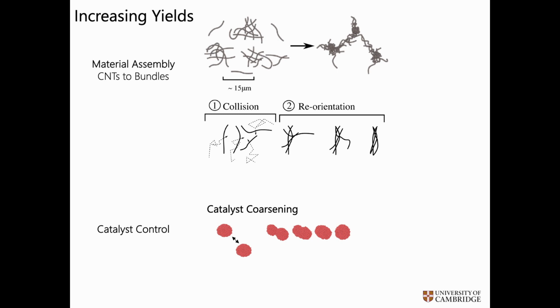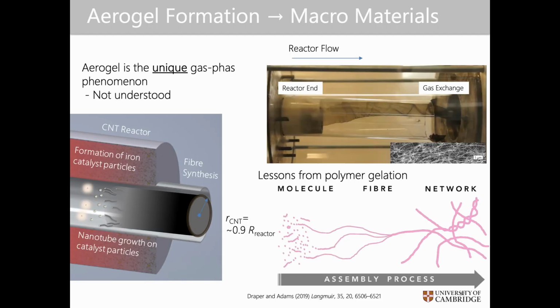And the other thing we'd like to understand is catalyst coarsening, and we'd like to be able to prevent that. We'd like to prevent that because we could get more catalyst to grow nanotubes if we prevent this process. And we've got, as I said, orders of magnitude improvement to make here. So on the first one, we can take some motivation. This is, again, another reactor running in our lab. We've got half a dozen of these things running. The nanotubes coming out, it's a slower process here where we're studying it a little more. And what we're looking for is emergent properties.